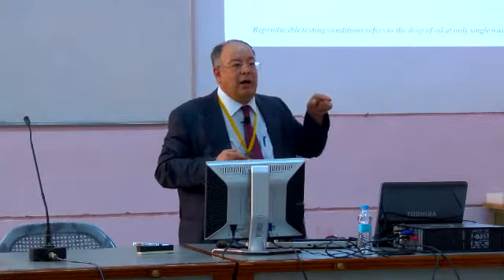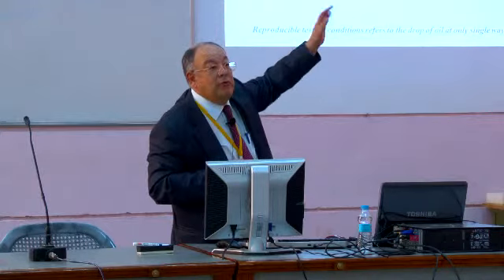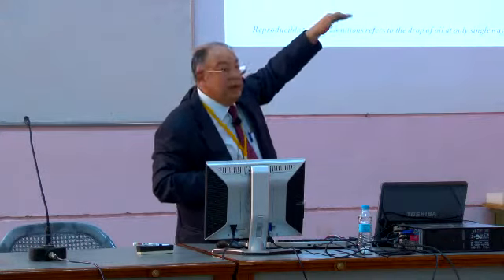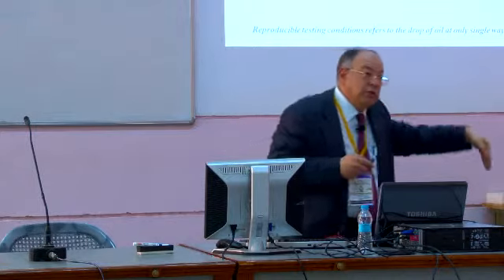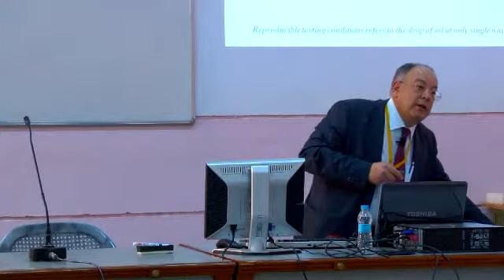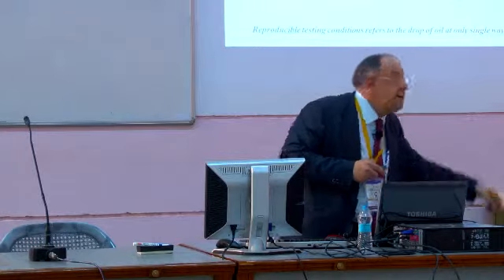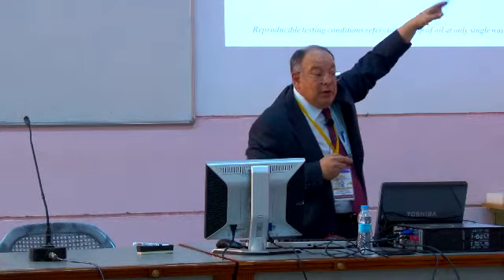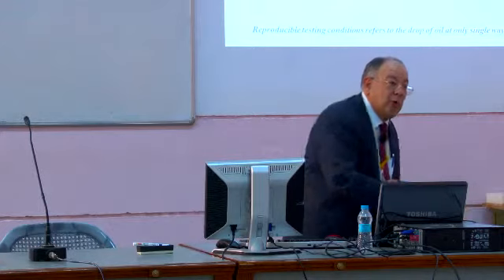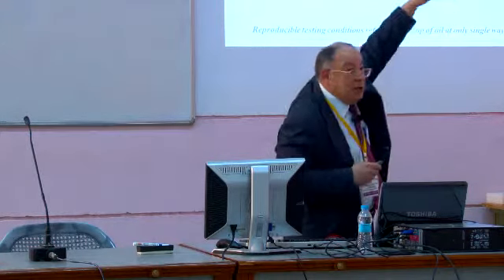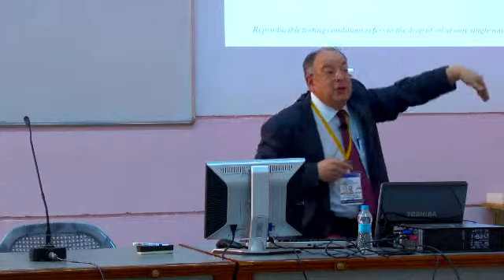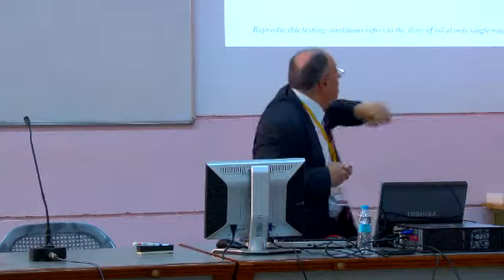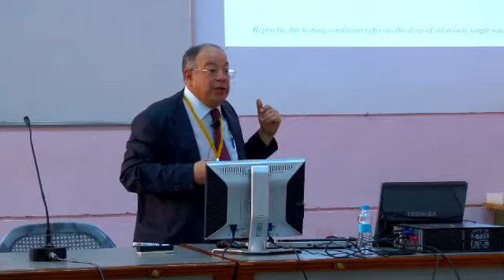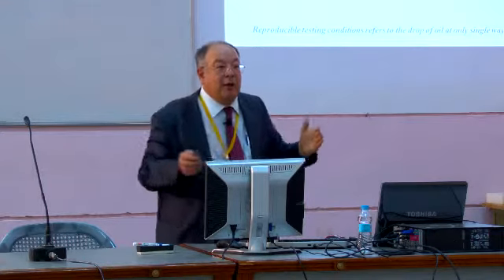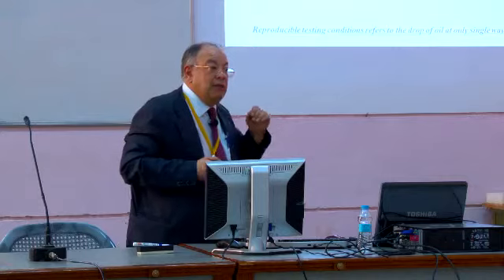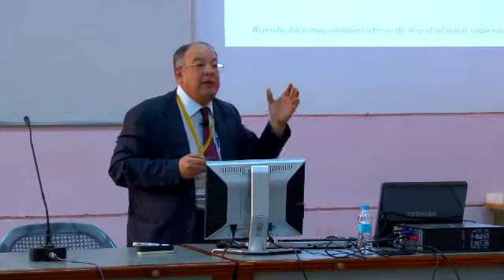I always say it's like painting a wall, and the wall is not fully painted - if you dip your brush into less paint, you don't paint very well. But if you have more paint, thicker paint, your wall gets fully painted. In the case of pin-on-plate, it is not well painted; the additive layers formed like islands rather than a full coating.